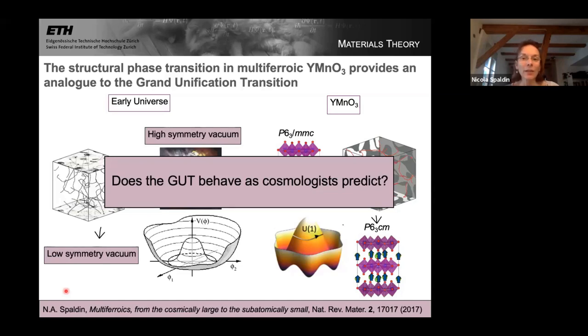And remember also this phase transition is up at 1000 Kelvin and we're measuring at room temperature. So if we were doing this within say 10 or 20 Kelvin of the phase transition, we would worry about the fact that the strings could still migrate. Of course they're protected, but they can get pushed out the edge of the sample, and if opposite ones meet together, they can annihilate. But we're really so far away from a region where the ions are moving readily that I think it's really, really stable. But it's a good question. I mean, it's certainly a destructive technique.